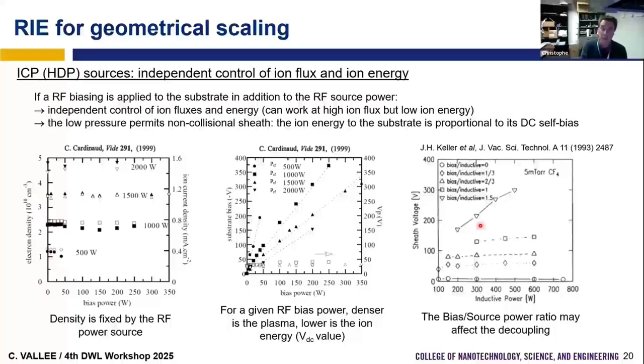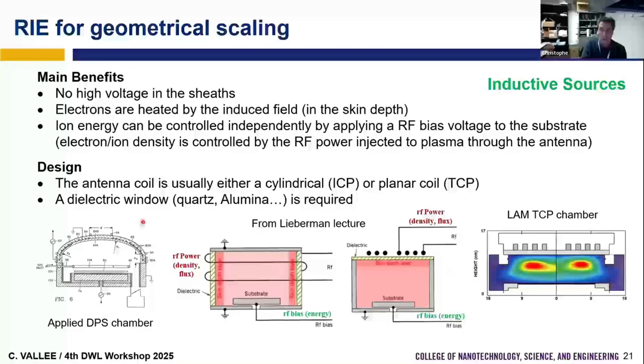Instead of using a single frequency CCP reactor, we can use what we call an HDP source. It's a new design with inductively coupled plasma to have an independent control of ion flux and ion energy. It was a second generation of plasma etching reactors used by the semiconductor industry, like the Applied DPS chamber with the coil all around the dielectric window, and an independent control of the substrate, or the Lam TCP reactor, where you have the coil here, and you apply the source power to the coil, and you have an independent control of the energy with the bias applied to the substrate. So what is interesting is that now we decouple the ion flux from the ion energy with this design.